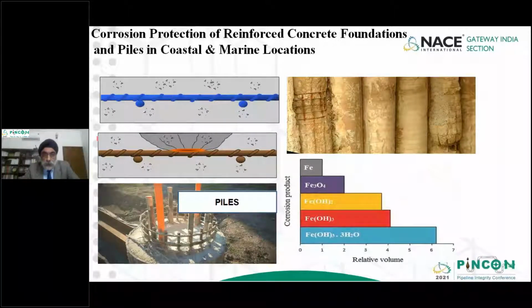So typically, this slide gives you an idea. There is a rebar which is embedded in concrete. The rebar is showing no corrosion, and the integrity of the concrete structure is well maintained. Due to chloride ions over a period of time diffusing through the concrete cover, this is the concrete cover over the rebar, the process of corrosion starts. When the corrosion process starts, the rust pushes the concrete up, leading to formation of cracks. When cracks get formed, it forms a direct path for the outside environment, which is primarily soil, to leach into the foundation and start accelerating the process of corrosion on the steel rebar.